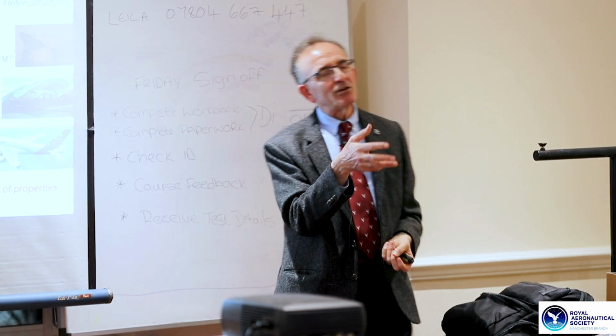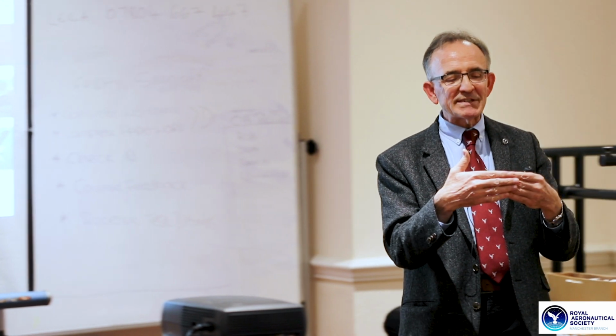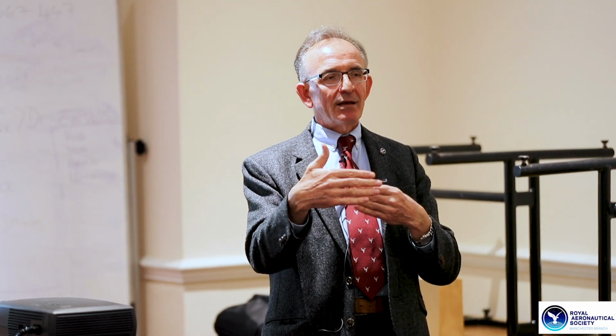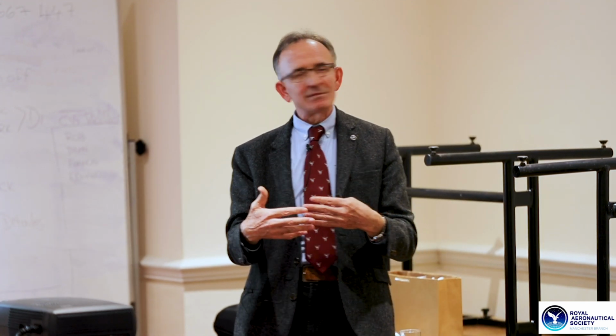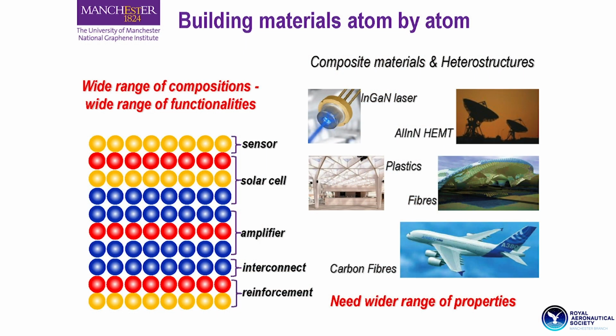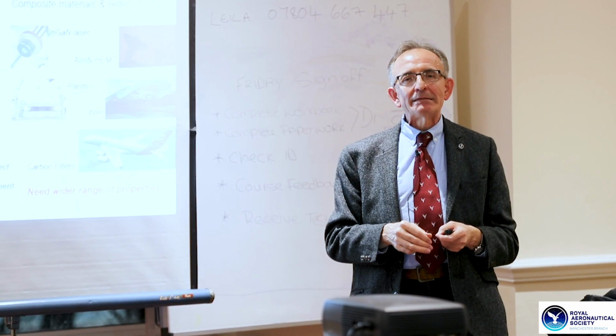And then we've seen at the beginning of the lecture that we can build composite systems layer by layer. But graphene enables us to build materials atom by atom. And then some of those layers can be the sensor, some others can be the solar cell where you store energy, and that energy runs the whole system with the amplifier and the interconnects all these layers, and some of these other layers can provide us with the reinforcement. They can give us the stiffness, they can give us the strength. So instead of building them layer by layer, we can go down to atom by atom. And each layer can have different functionality.